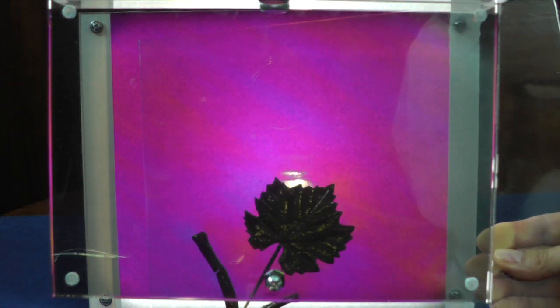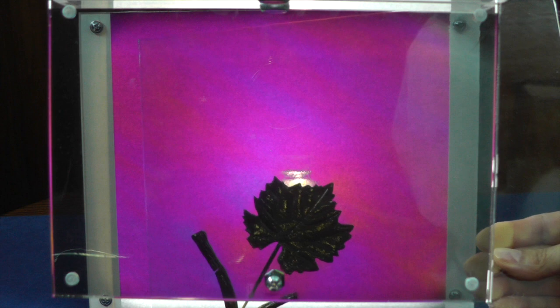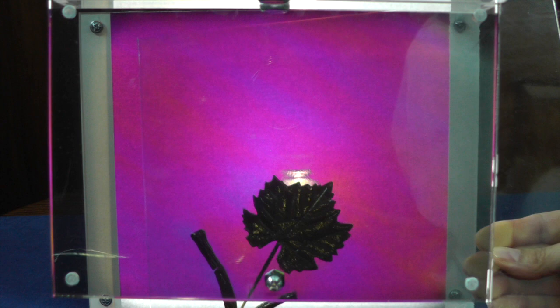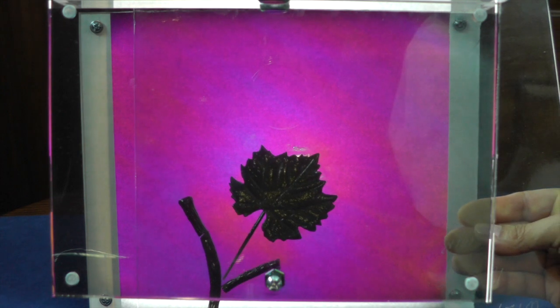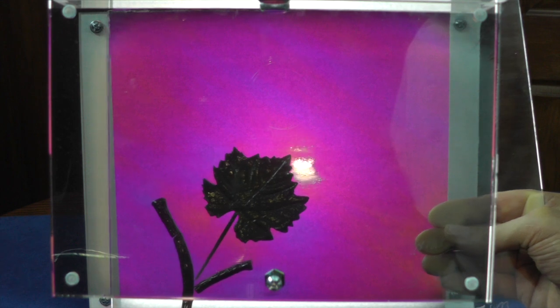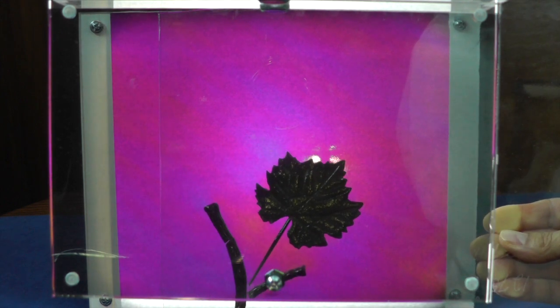Now, the only exception I would say is when you're fusing glass. Glass that's only like 6 millimeters thick and maybe, let's say, 8 by 10 inches in size, you want to have no strain at all in the glass because of the thickness of the glass. It doesn't have much strength at 6 millimeter, and that stress can sometimes be enough to crack the glass.